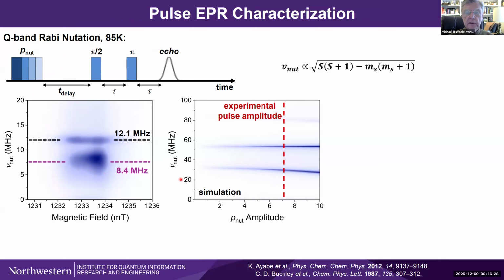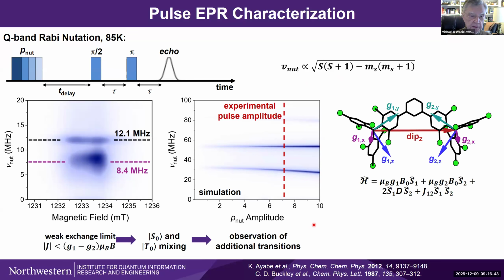It turns out that the singlet triplet gap in this case is small enough that this equation that normally one uses for the nutation as a function of spin multiplicity is not strictly valid. So you get a bit of both. And in point of fact, I'll show you later how this can actually be eliminated. What we have here is a system, though, that has approximately a 12 angstrom distance center to center between the two radicals, and I'll come back to that in a moment as well.